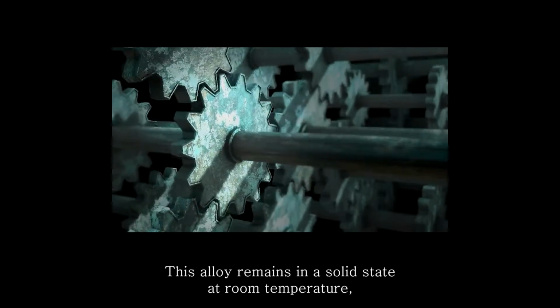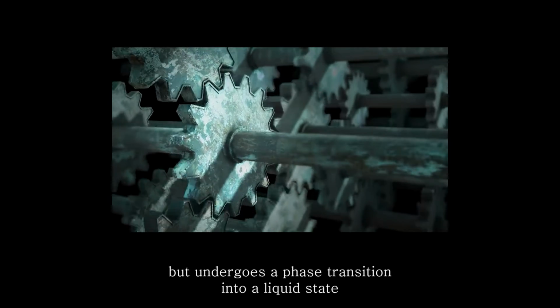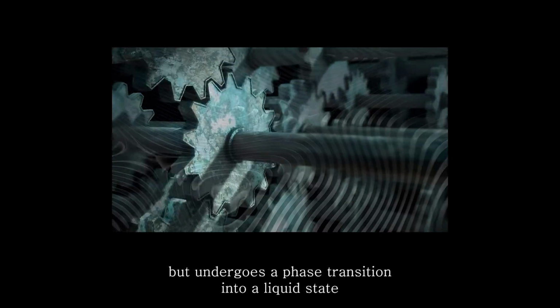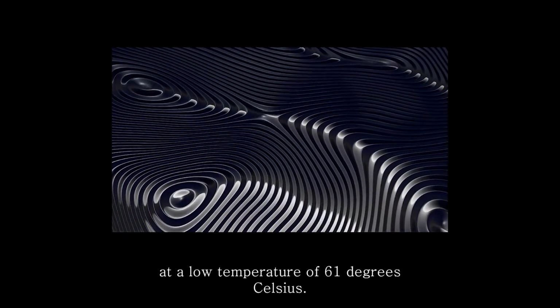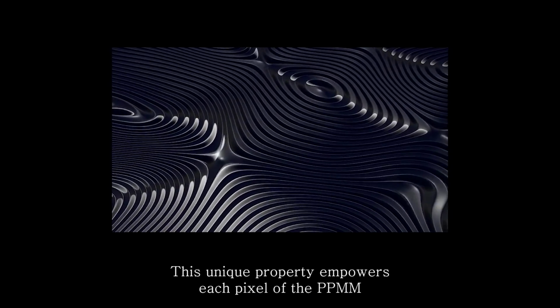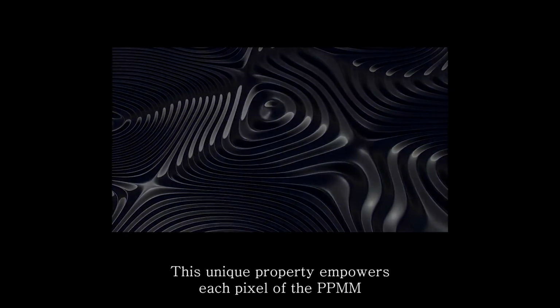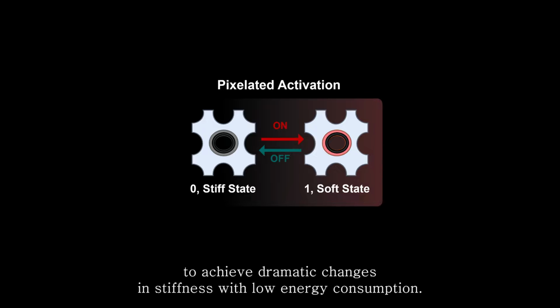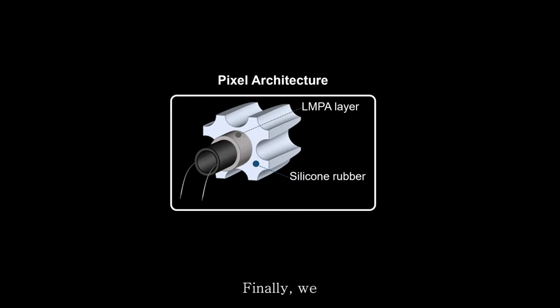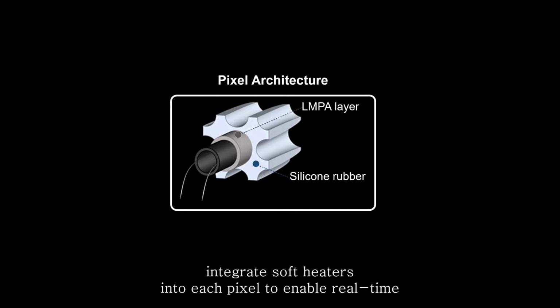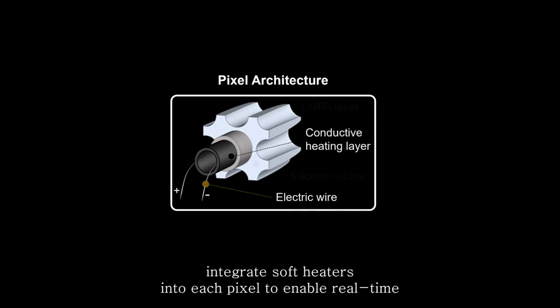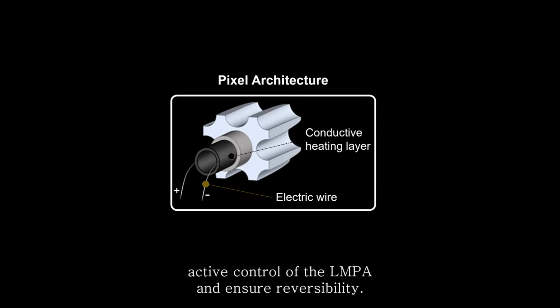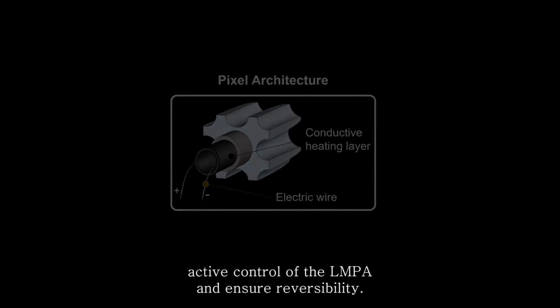This alloy remains in a solid state at room temperature, but undergoes a phase transition into a liquid state at a low temperature of 61 degrees Celsius. This unique property empowers each pixel of the PPMM to achieve dramatic changes in stiffness with low energy consumption. Finally, we integrate soft heaters into each pixel to enable real-time active control of the LMPA and ensure reversibility.